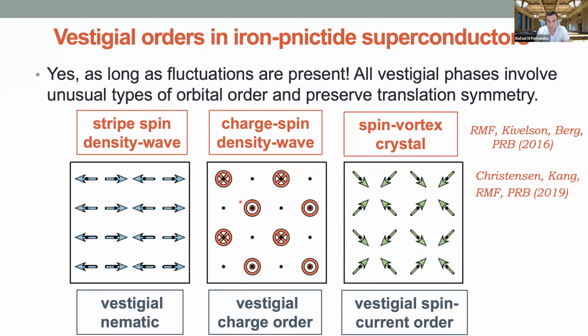The charge-spin density wave has a vestigial charge density wave, where these sites have a non-uniform phase, where you have Néel order in one sublattice and no order in the other. And in the charge order vestigial phase, you have larger charge in one of the sublattices than the other.